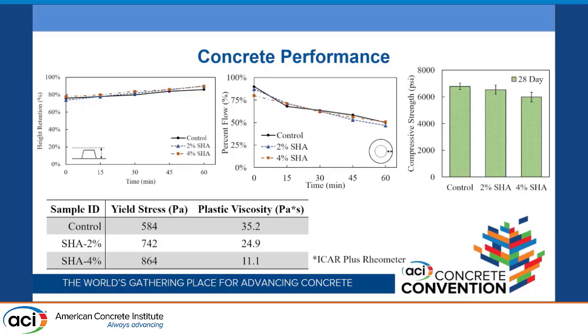We found a slight decrease in compressive strength at 28 days with the inclusion of the self-healing agent, about 10% at 28 days with the addition of 4% self-healing agent, going from about 6,750 psi to about 6,000 psi.